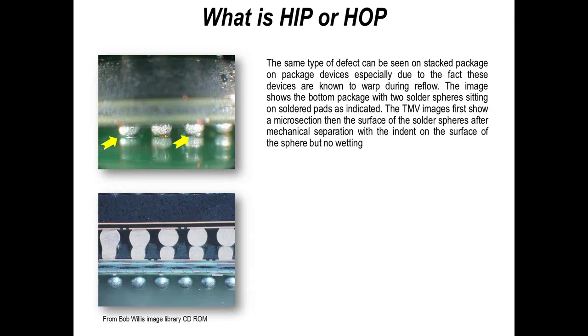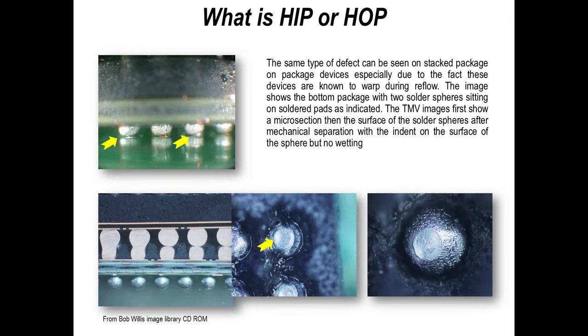And this is because the package hasn't settled down quick enough, and the fluxing material, the flux being applied to those two surfaces, hasn't got sufficient energy to allow it to clean those surfaces to allow reflow to take place successfully. So that's a sort of classic example of what you might expect to see on this type of package. These views now I show you, again, I'm pointing out the depression in the solder sphere. And then on the right-hand side of that image, you can actually see the flux material physically on the ball, but again, no evidence that the two have reflowed together with the adjacent ball.